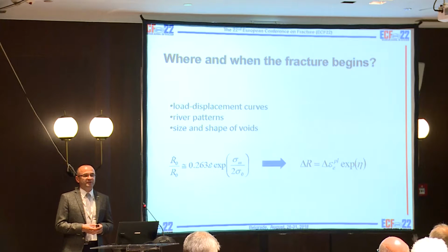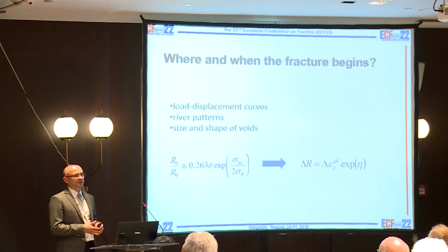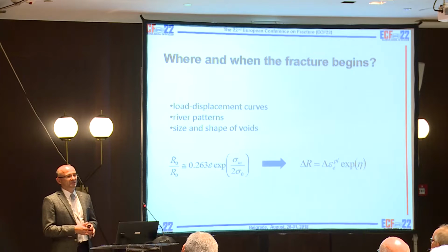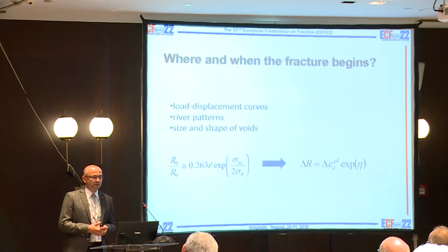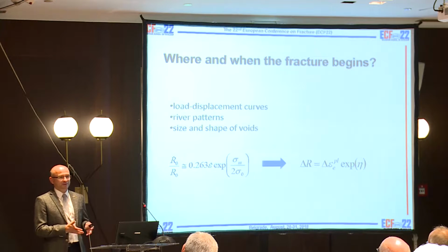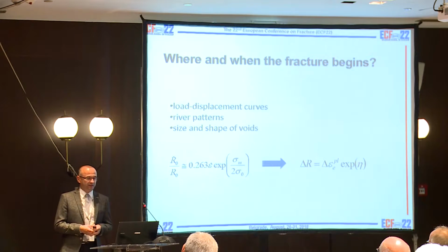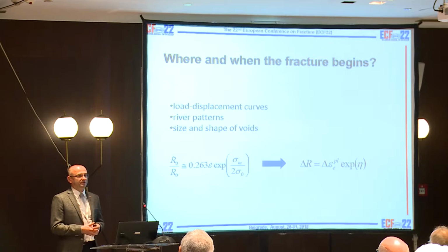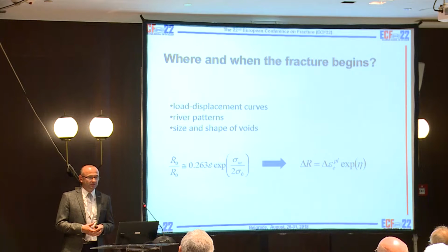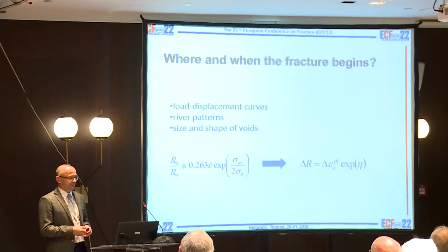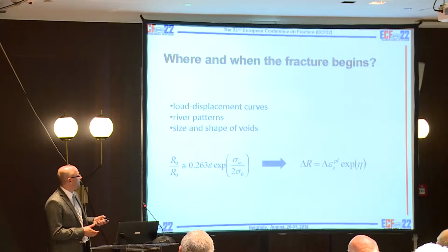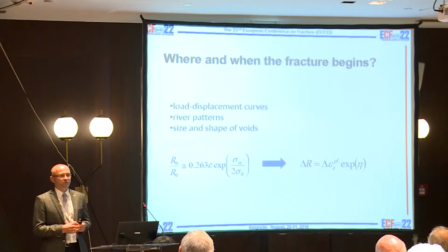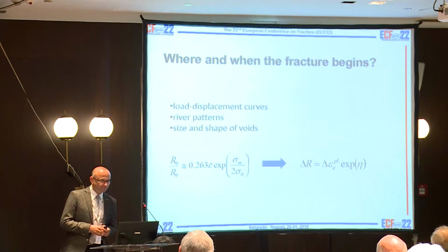However, we have a problem with the ductile mechanism, because initially we wanted to use shape and size of voids. However, even under a microscope, we are unable to find a place where we are sure that this process begins. So that's why we use the Rice-Tracey formula for a spherical void, and we slightly change it, and this equation on the right very roughly describes increase of void. It was enough for us.